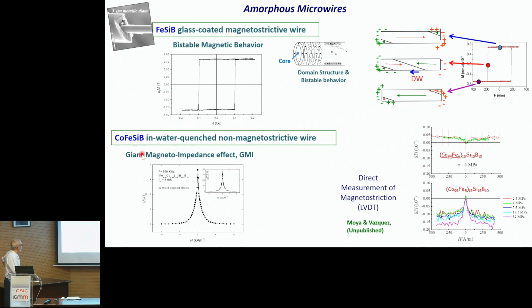And those cobalt iron silicon boron alloys with zero magnetostriction have the so-called giant magnetoimpedance effect, which is relevant in many sensor applications. I would like to say that although we have been working on this for almost 30 years, there is still very interesting experimental work to determine the magnetostriction constant of these alloys. Just changing the composition a little bit, we get a magnetostriction from positive to negative, and this is probably the smallest value that has been measured. I'm not going to talk about magnetoimpedance, but if somebody is interested, we can talk later.